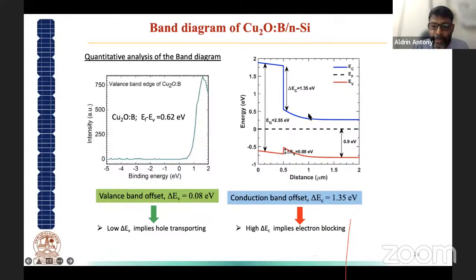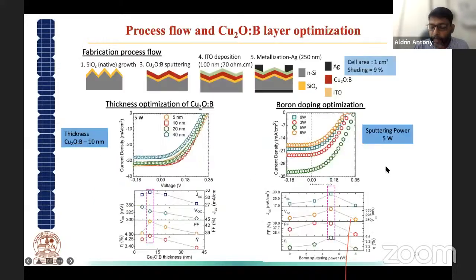So this selectively allows only the holes to move in one direction and blocks all the electrons coming in this direction. And so copper boron oxide can effectively be used as a HSL contact for a crystalline silicon solar cell. And this is what we optimized with the different solar cells that we fabricated. And these are the different IV characterization curves we did with the optimization of copper boron oxide for different thicknesses. And the best thickness that we found was the red one, that is 10 nanometer.